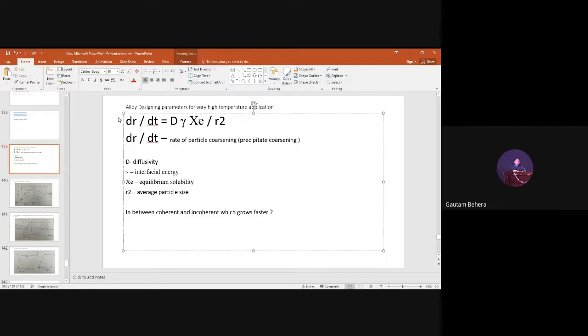But the rate of particle coarsening dr/dt is inversely proportional to r square here. R square basically means it depends upon the average size of the particle. If the average size of the particle is smaller, the particle becomes coarser with time. But if the average particle size is bigger, it will not coarsen much, right? But the interesting point we have to notice here is Xe, the equilibrium solubility.